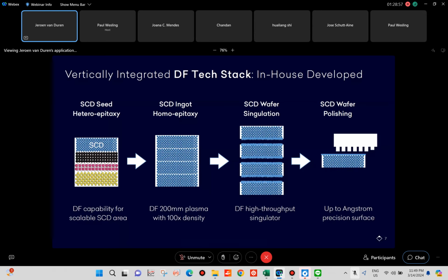Once you have these ingots, obviously these ingots need to be sliced. So we had to develop this ourselves, a high throughput singulator that's scalable with wafer size and provides low kerf. So it's important with wafer singulation that it's high throughput and low kerf and scalable. And then once these wafers are sliced, these wafers need to be polished, and we polish them up to an angstrom level smoothness.